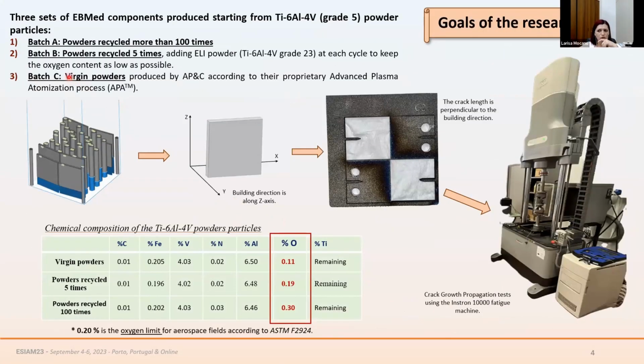Yes, if I understood, did you ask if the type B, which is the powder recycled 5 times, has some new powder? Yes. At each cycle, we added new powder, which is basically the same titanium alloy, but it's grade 23 because we wanted to keep the oxygen content low, because this alloy is characterized by a lower oxygen content. Because we know from the literature that we have this problem: as the recycling cycles increase, we have an increase in the oxygen content. Okay, thank you.